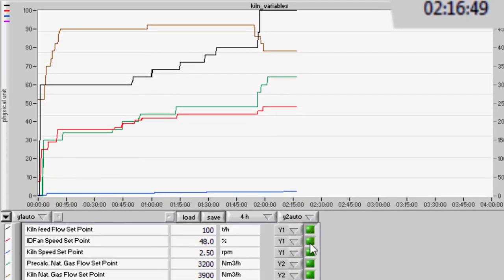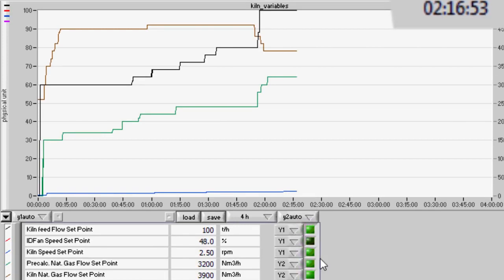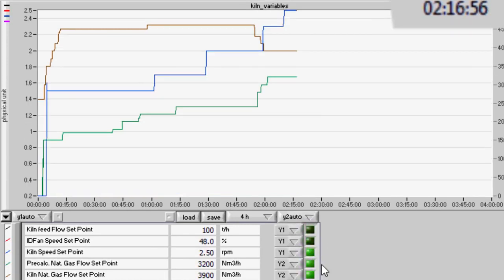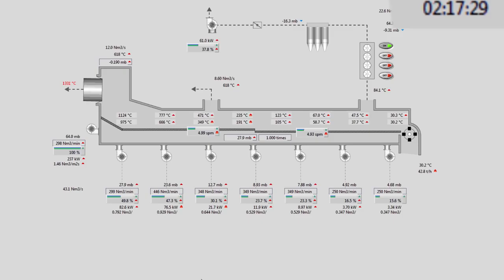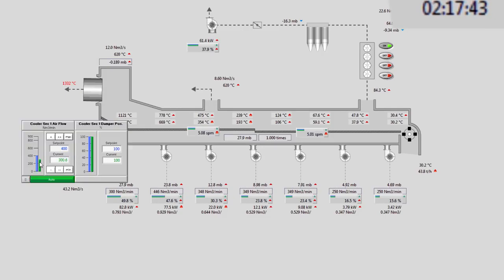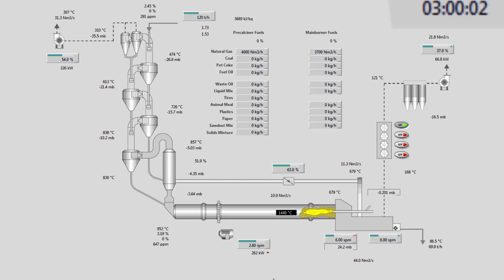Let's clear up these graphs. The green line, pre-calciner fuel, and in brown, the main burner fuel. Notice that they're converging towards each other. Ultimately, we will reach the 60% pre-calciner to main fuel ratio. The clinker cooler, I have started the last 4 fans and set them all to auto mode. I see that fan 1 cannot deliver the flow. It means that there's too much material on top of the grates. I will need to speed them up.